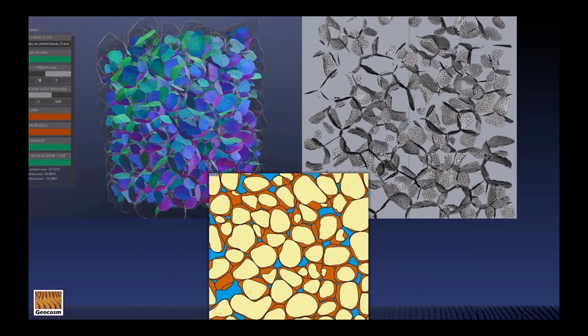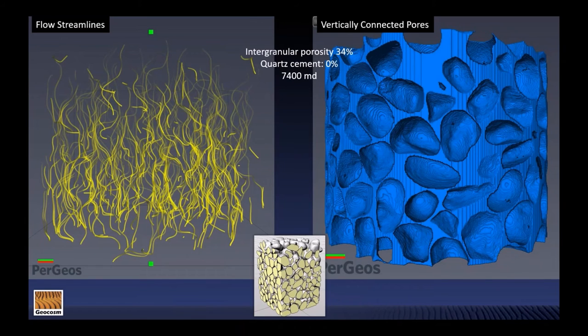The purpose here, as a proof of concept, is to show how we could take the results of these types of simulations and then use them in so-called digital rock physics models that have been developed to try and predict rock properties from micro CT scans of natural sandstones. In this case, however, we're going to use simulated pore geometries through geologic time. And so what we're looking at here is that same 3D grain pack. On the right, this thing that looks like blue Swiss cheese is a rendering of the pore volume as if the pore volume were solid. So these pock marks here represent where we have the quartz grains.